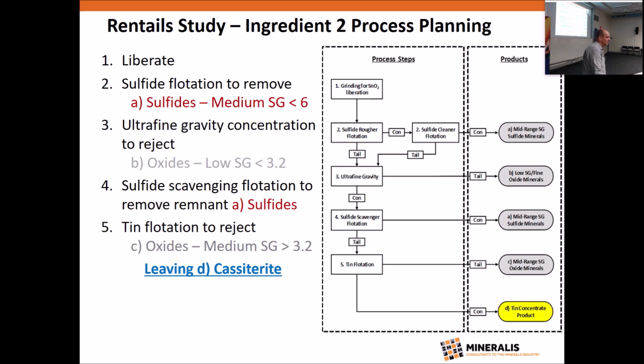So fundamentally, the process plan was a bit like the whack-a-mole arcade game. You just smack everything that sticks its head up that's not cassiterite. So the first step is to get the cassiterite liberated, and then use flotation to get rid of the main competition, and that was the Group A sulfides. We then used the ultrafine Falcon to effectively de-slime the material and get rid of the Group B low SG oxides. And there's always been a wicket-keeping sulfide scavenging stage required at Renison, and it's mainly been used to get rid of any remaining Group A very fine and slow-floating sulfides, in particular arsenopyrite.